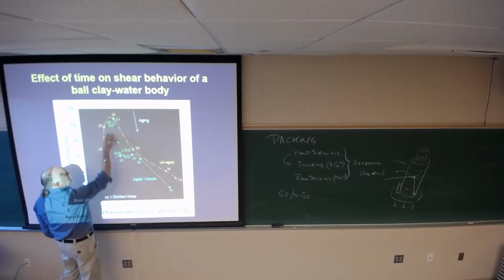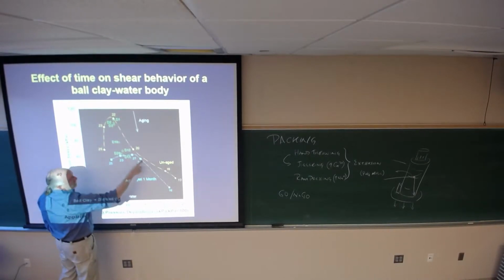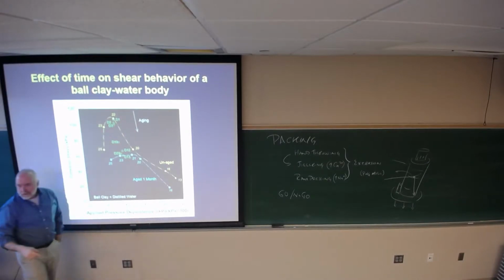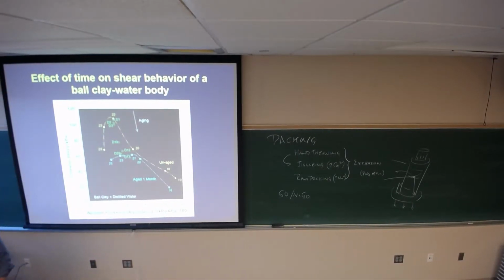Look at the change in the slope. This point moves, 20 moves, 16 moves. Okay, what's happened? Ionic solution. Yes, the clay is aging. And as the clay ages and you increase ionic strength, what you see is a decrease in that cohesion stress. The body gets softer as it sits around and ages.